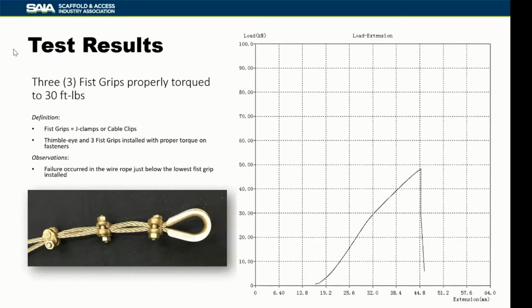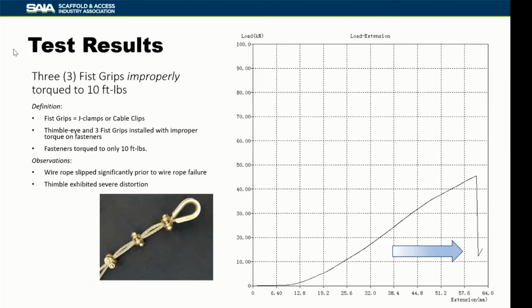Again, our failure occurred in the wire rope just below the lowest fist grip that was installed. The breaking force was right in the same range as our mechanical swages, up around 10,800 pounds, and the elongation was more along the lines of the aluminum, where it got a little bit longer than what we saw with some of the other ones. When we compare that to improperly torqued fist grips, which were torqued to only 10 foot-pounds, you can see that our elongation increased dramatically.